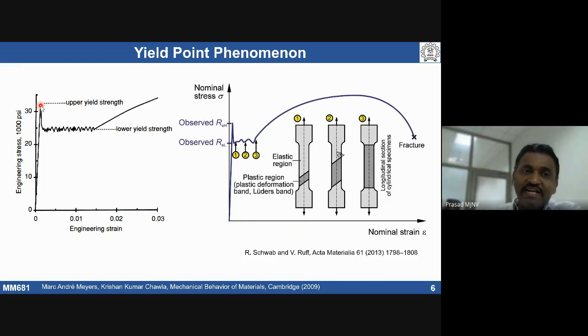Once you increase the strain rate, the dislocation velocity is directly going to influence my internal strain rate of the material. That means though I'm applying a particular strain rate, initially a small amount of deformation can lead to an increased strain rate locally. So there is going to be an instability region.